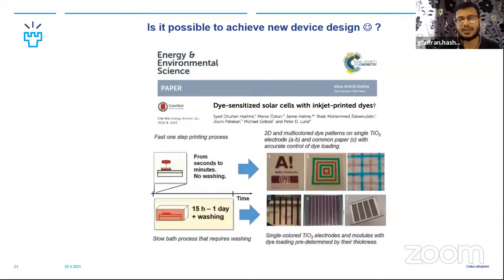So we showed that the traditional dye soaking process needs overnight soaking of titania electrodes in a dye bath, and then you get a monolayer. But we replace this process by making a concentrated dye solution that can be filled in the cartridges, and then you can sensitize, and you can even pattern multiple dyes on a single titania electrode.